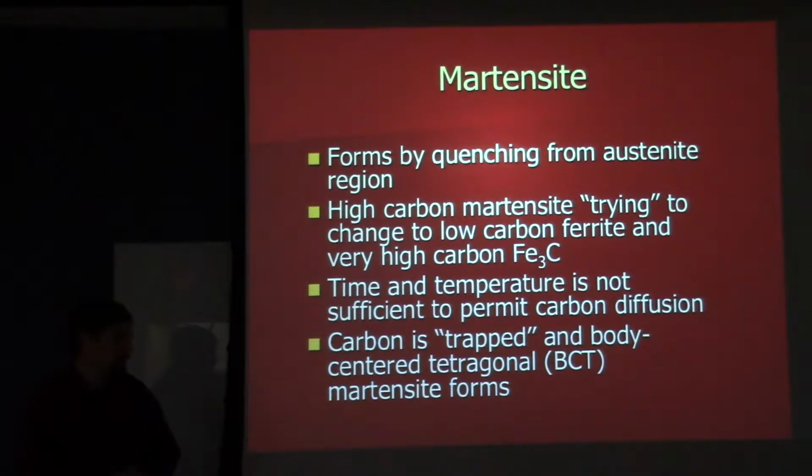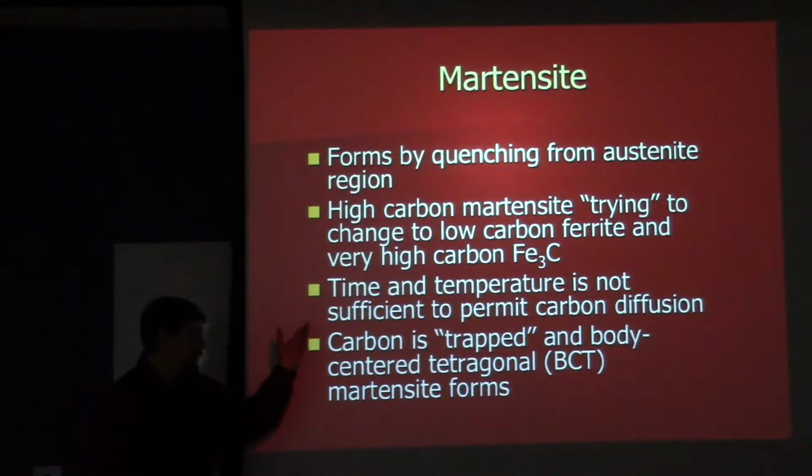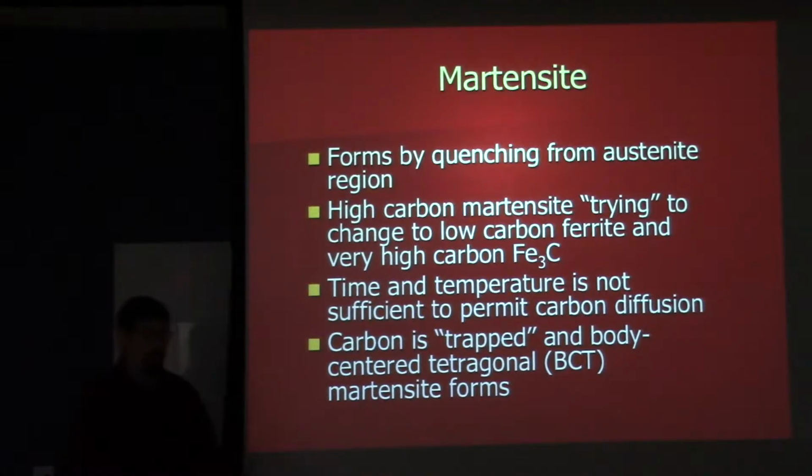otherwise have. One of the ways I explain it is it messes with the slip planes, because it distorts the slip planes, and now we can't have slip because they're uneven. So in this case, for the martensitic transformation, it's happening very quickly. There isn't time for diffusion to occur, and so we get that locking effect.